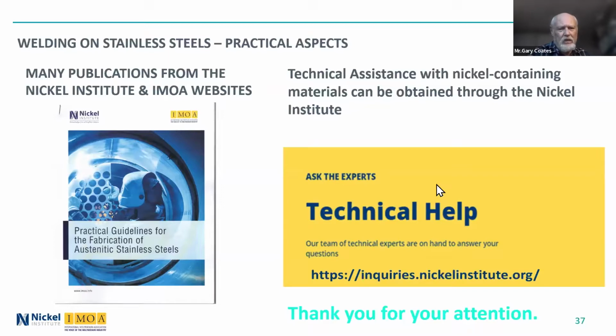Okay, there's another one related to tube sheet joints on an Alloy 600 weld overlay. And again, because on an overlay you have dilution of the base metal, it depends on whether it's one layer of overlay, two layers, or three layers to actually know what you have on the surface there. And so really we need more information there. Please contact us through the tech service line with the details.